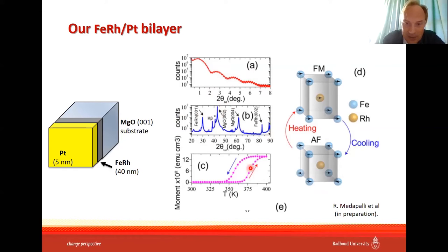For me, what is most important here is this hysteresis loop. This is the dependence of the magnetization as a function of temperature. So you can see here that upon increase of the temperature, the magnetization increases. Then you decrease the temperature, the magnetization decreases, going nearly to zero. And because it's a first order phase transition, you see temperature hysteresis in this picture. Similarly to magnetization reversal, where you have hysteresis in the magnetic field dependence of the magnetization, here you have hysteresis in the temperature dependence of the magnetization, and the reason is the same in both cases: it's a first order phase transition. In a certain range, both phases, the high temperature phase and the low temperature phase, can coexist, and the hysteresis appears.